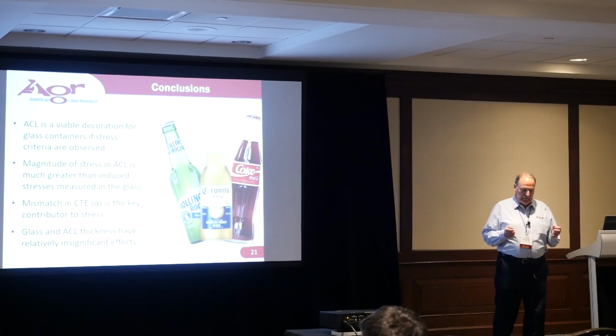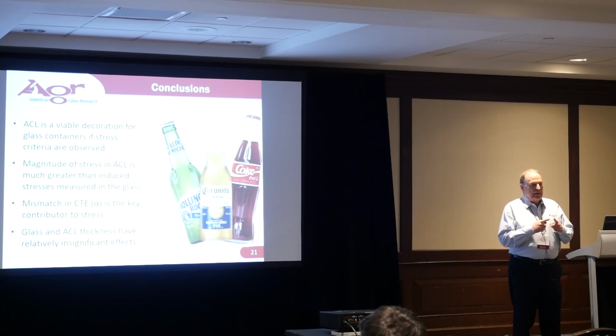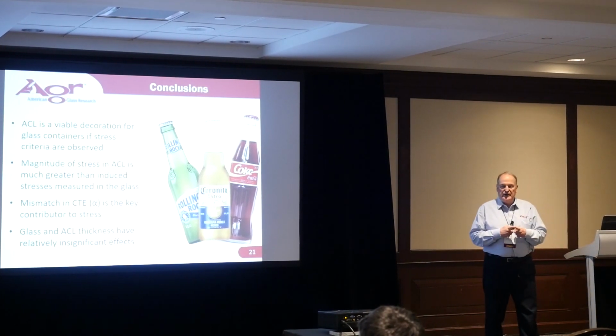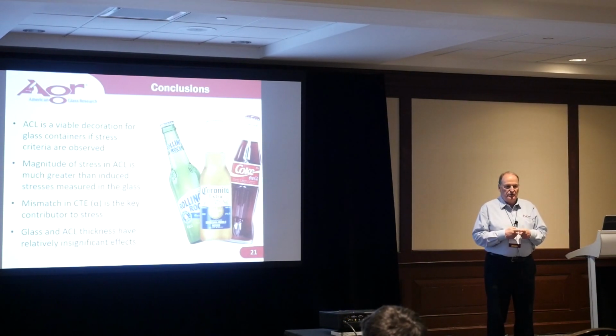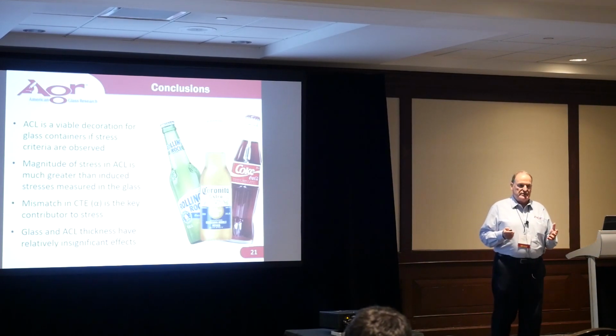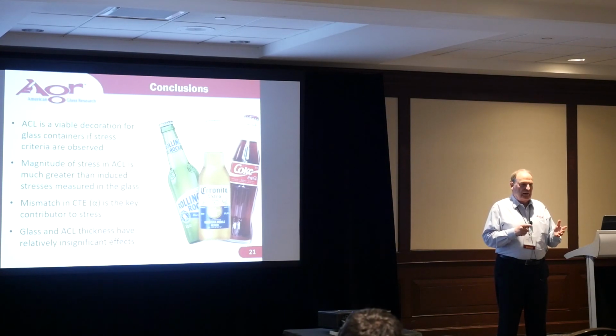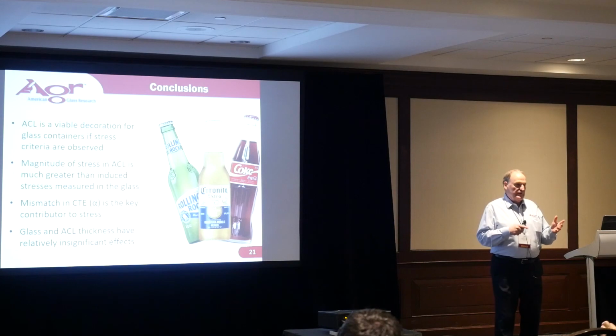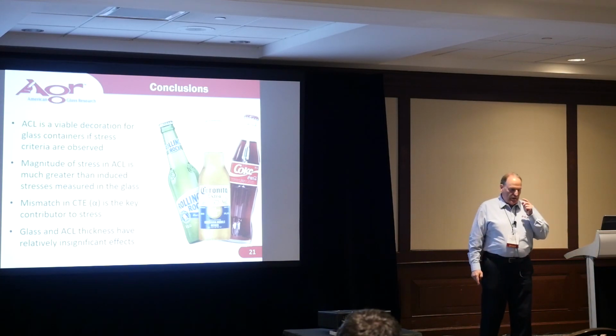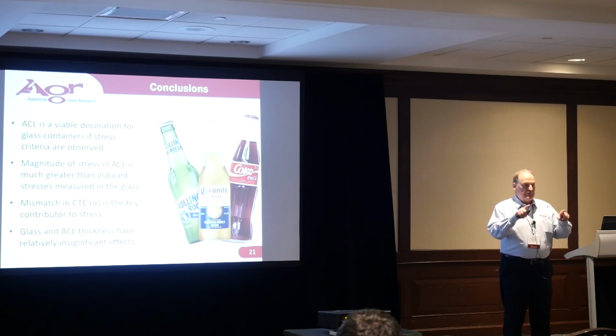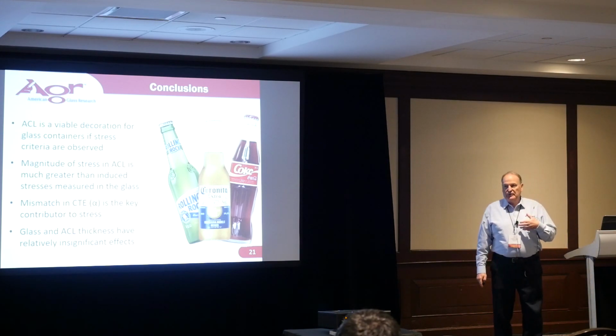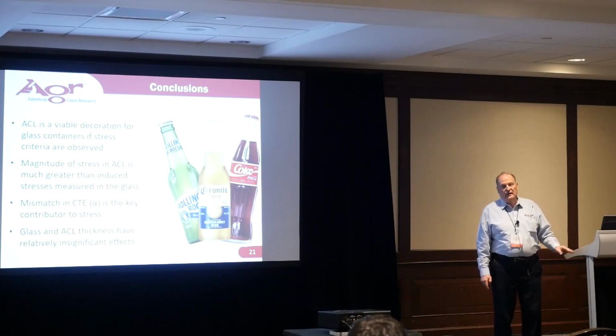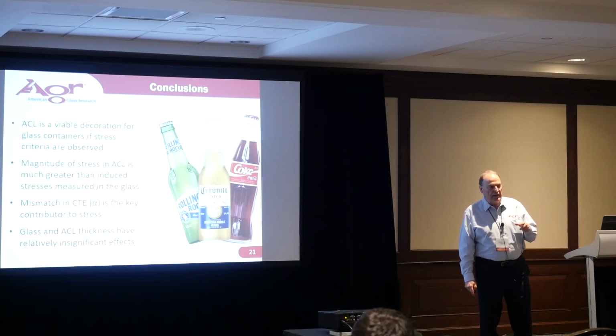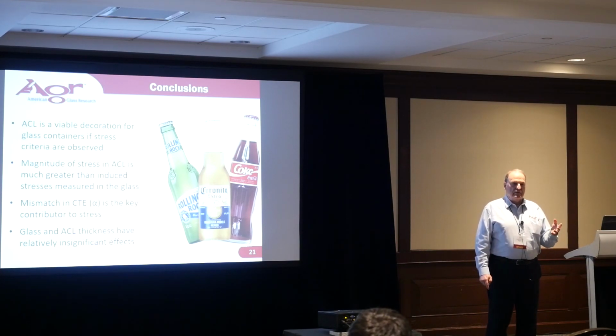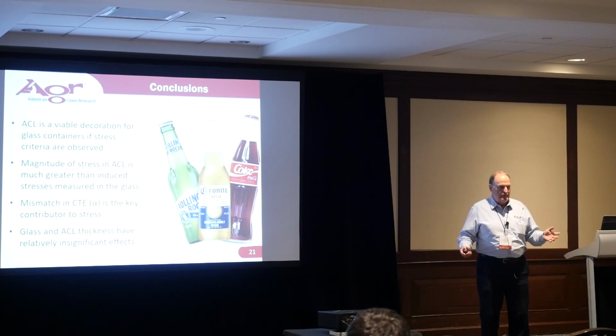Now, I mentioned earlier that it's very difficult to get an exact match. And I don't think that's a problem with the suppliers of the ACL. I think they have a pretty good handle on what they're doing when they create the ceramic labels. I think the problem with the mismatch lies more in the hands of the glass manufacturer. Let me give you a small example. We had a problem where the viewing windows on microwave ovens or on regular ovens were fracturing. And they were decorated. So they sent them to us, and we measured the stresses that were inherent in the glass. And we found that the coefficient of expansion of the decoration was higher than the glass. When we reported that back to the glass manufacturer, he said, it can't be. Our glass hasn't changed.